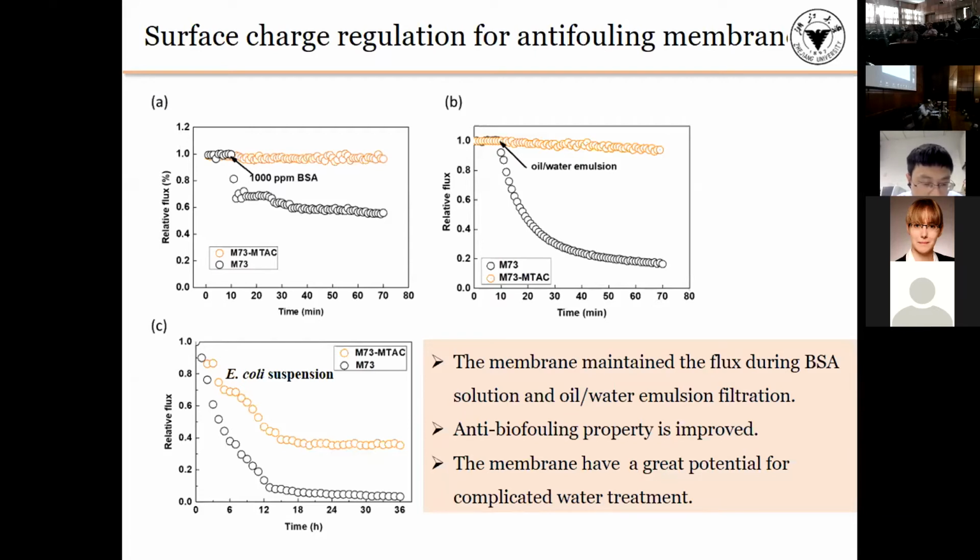Therefore, a more hydrophilic and non-charged surface containing a polyampholytic copolymer was formed through a simple surface grafting method. Another reason for the low bacteria adhesion on the modified membrane was the antibacterial property of the ammonium groups on MTAC. This property effectively prevents bacterial growth after the surface adhesion.